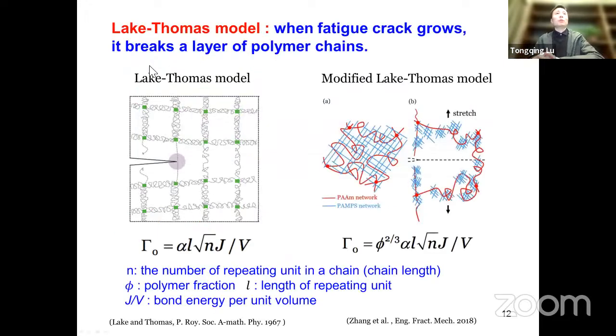So now we look back to the literature on the fatigue of rubber. There's a famous model called the Lake-Thomas model. This model assumes that if a fatigue crack grows, it breaks a layer of polymer chains, and the energy to break a layer of polymer chains can be easily estimated. Alpha is a prefactor. L is the length of the repeating unit, meaning the length of the polymer chain. Because the polymer chain has many carbon bonds, we call it the length of repeating units.